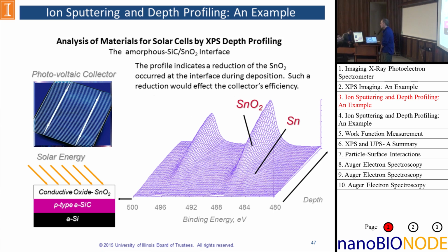Okay, so this is one example of XPS combined with ion sputtering that I'd like to show. This technique is known as depth profiling. Tim went through this in quite a bit of detail, but you can actually do some depth profiling in XPS. In most cases, though, with XPS, because of the physical interactions of the ion beam with your material, there is quite a bit of chemical and electronic damage done to your material.